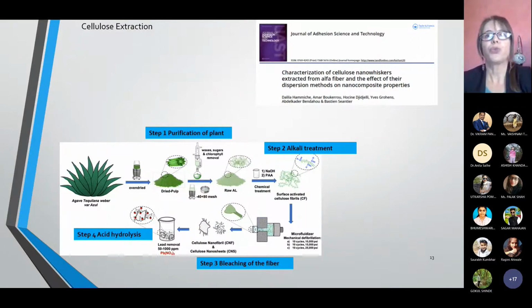Fats, wax, and oil are removed from the powder simply by refluxing in a Soxhlet apparatus for 24 hours with an acetone ethylene mixture. Then we proceed to the second step, which is the alkaline treatment. Here in this step, the fibers are treated with sodium hydroxide solution. This treatment was done 5 times to remove constituents other than cellulose from the fiber. The constituents other than cellulose, as I said, are hemicellulose and lignin. This removed the greater part of lignin and a large part of hemicellulose. After each treatment, the fibers were filtered and washed with distilled water until the alkali was removed. Here I want to say that the pH will reach 7.